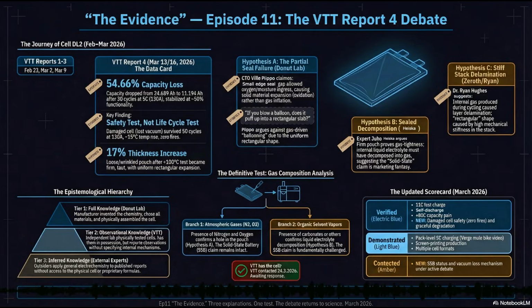One test. And what about Hypothesis C, the delamination theory? How do we prove or disprove that? Cross-section imaging. You take the cell, you physically cut it open, or you put it through a high-resolution CT scan. Just look inside. Right. If you see the microscopic layers physically separated with gas pockets ballooning between them, the delamination theory is correct. And if not? If the layers are physically intact and tightly packed, but visibly rusted and oxidized on one side, Donut Lab is correct.